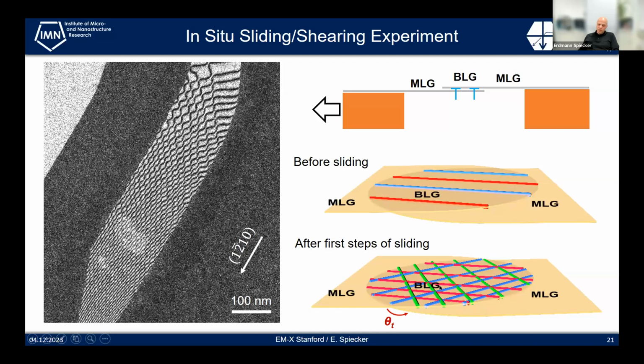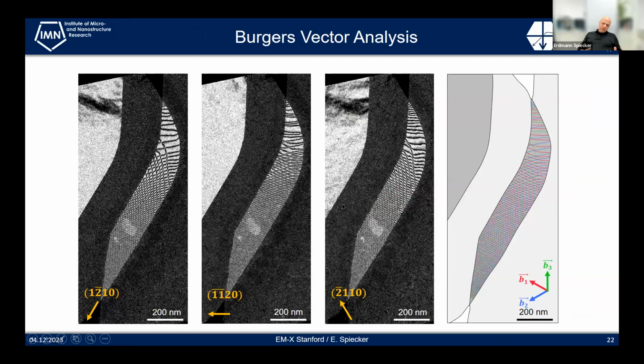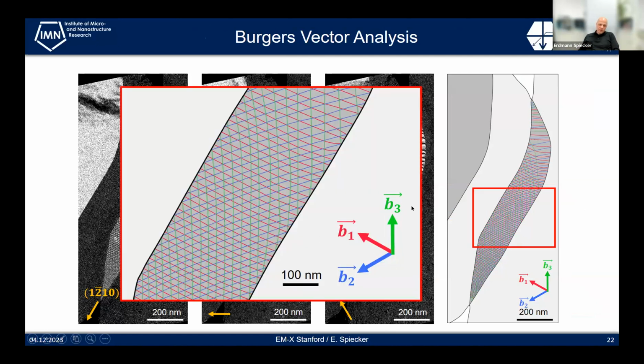So the almost pure twist boundary. As I mentioned before, in order to completely evaluate such a network, we have to combine 3 types of, or at least 2, dark field images, and then we can derive the full set of dislocation lines and Burgers vectors. And here it's enlarged, and you see the 3 types of Burgers vectors. And actually all dislocations here, the green is parallel to the green arrow, the red parallel to red and blue, and so on. So it's almost exclusively made of screw dislocations.